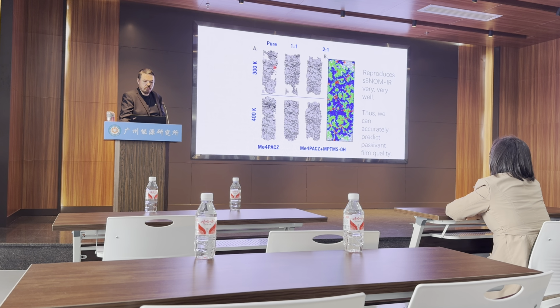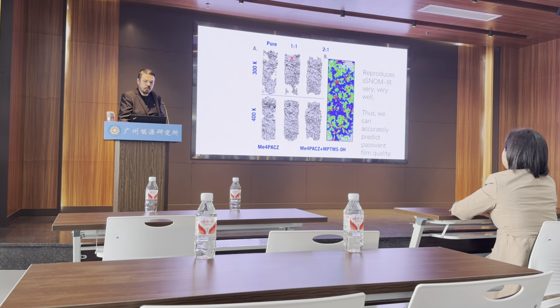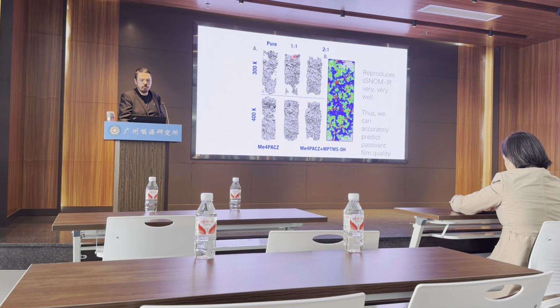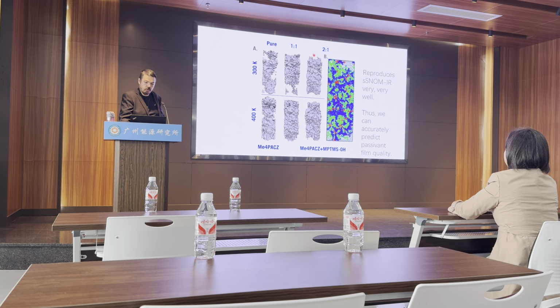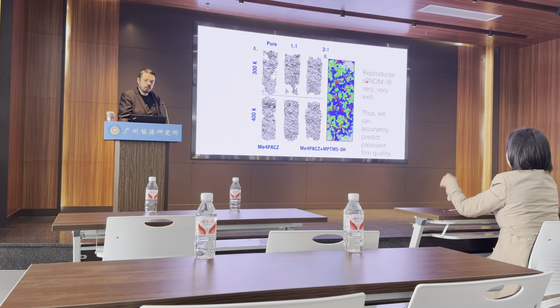So with just Mo4PACZ, you can see we have holes here. So it aggregates way too much, and we end up getting these holes in the material. So that means the perovskite and the nickel oxide can touch, and that's no good. And then for the mixed material, if we add a little bit of MPTMS-OH, we get an improvement, and then we add a lot of MPTMS-OH, the improvement is even more noticeable. And then we did this before the IR experiments.